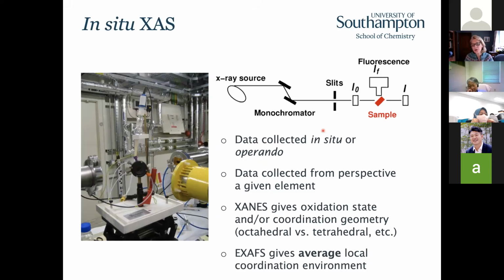So the data that I'm going to show you today are really in situ measurements, but people use these terms interchangeably now. And I'm not an advocate of this. I think we need to make this distinction so we know what we're talking about. The advantage when we start looking at these complex materials that we're now using in electrocatalysis is that we can collect the data from the perspective of each element. So I'm going to give an example of a platinum tin catalyst. And they were able to collect the data from the perspective of the platinum and the tin. And by looking from both directions, we understand the material in much more detail.